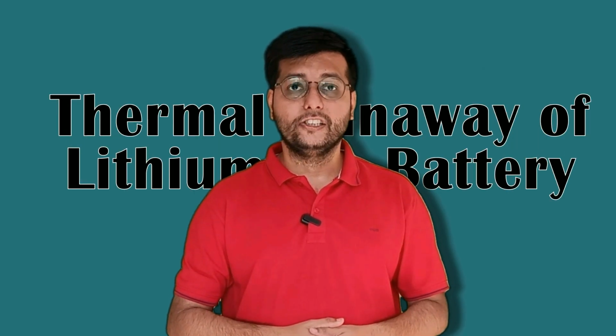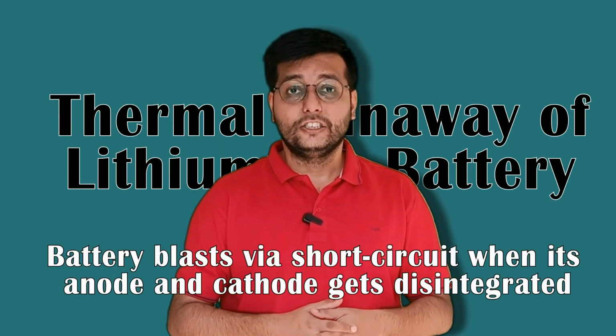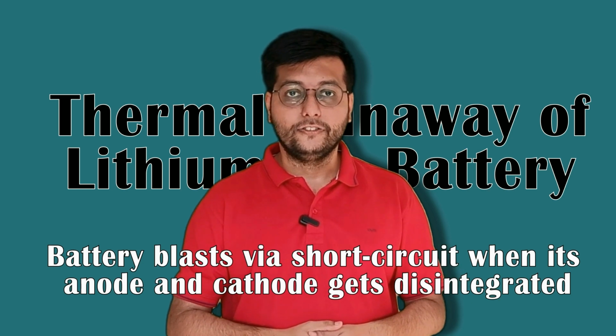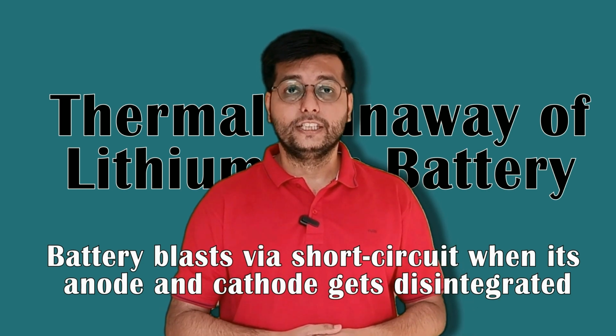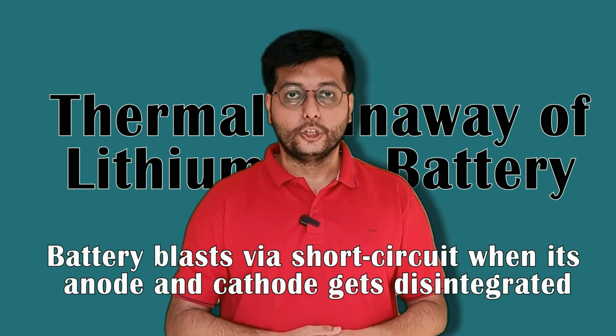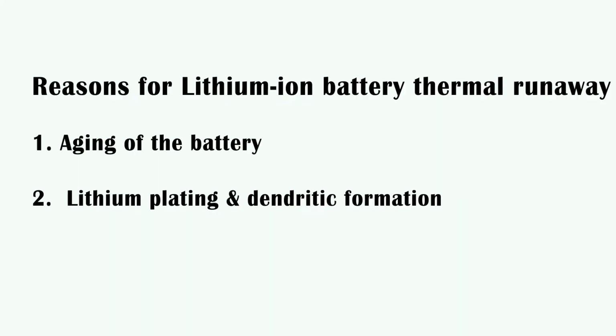A lithium-ion battery undergoes thermal runaway when it gets deformed, like through an accident of the electric vehicle, where its anode and cathode get disintegrated, resulting in a short circuit. Thermal runaway of lithium-ion batteries may also occur due to defects inside the battery from aging, or due to lithium plating and dendritic formation upon overcharging. Improved build quality of the lithium-ion batteries and auto cutoff upon overcharging may reduce the risk of thermal runaway.